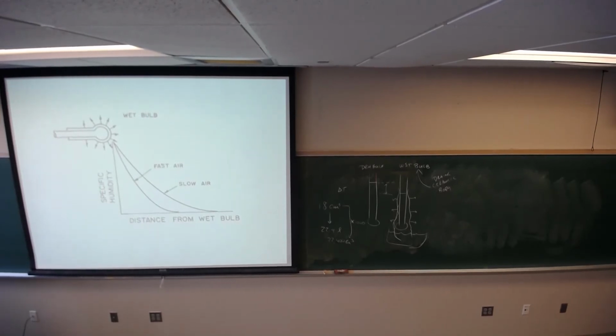Okay, this shows you that if you were to take this wet bulb, dry bulb thing and leave it stagnant, what you find is that the humidity would seem to be different if you move air around it, okay? And the reason for that is that in slow-moving air, the humidity would appear to be greater, okay? And that means that the difference in temperature between the wet and the dry bulb are closer together, right? So they're closer together, your humidity is reduced, okay?